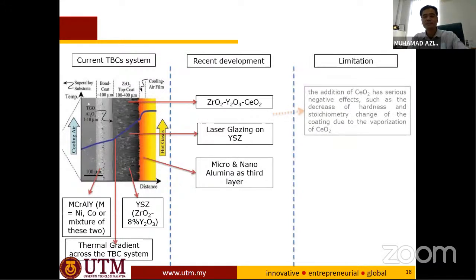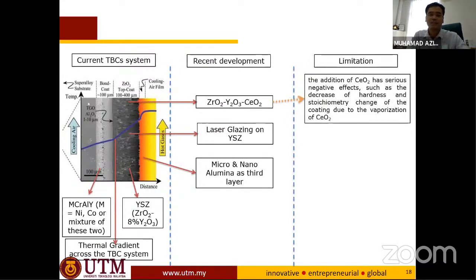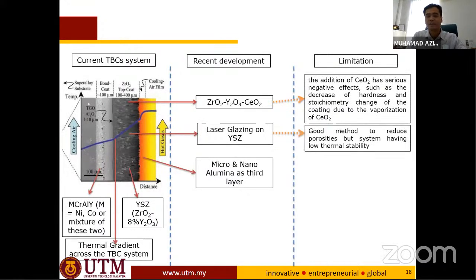Right, so the limitation, of course, is that the addition of cerium has negative effects, such as a decrease of hardness. If you're talking about the laser, it is a good method to reduce the porosity, but the system has low thermal stability if YSZ is used. Now in my research, I add another layer here, which is an alumina layer. This alumina layer is not TGO, not thermally grown. This is basically a deposited alumina layer. So this can reduce the TGO growth.